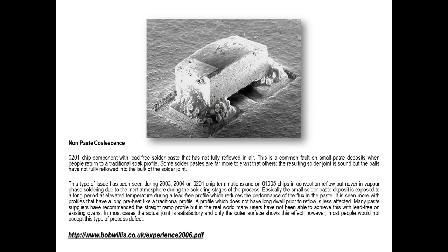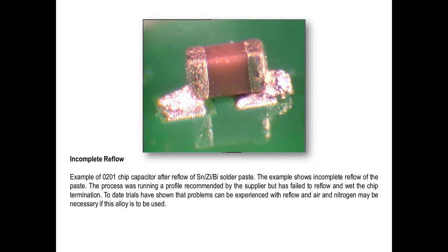And again, more recently, with my trials on the ultra small chip components, we've seen this again when moving to a type 6 paste powder. If you can run type 4 or possibly type 5 particle size for the very small packages, it shouldn't be so much of an issue. But again, you need to evaluate the paste for that particular application. Vapor phase convection shouldn't be an issue. And in all honesty, when I microsectioned this particular joint you see on the screen now, it was a good joint, but I'm sure a lot of other quality engineers wouldn't have accepted it because of the spotting, warting, or graping, as the term now most commonly used for this.